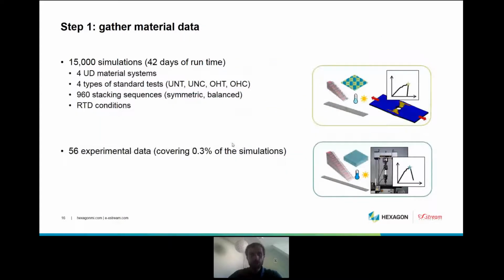Okay, so step one, like we mentioned, is to gather the material data. Here, what we have done in the following exercise is perform something like 15,000 simulations. So it's approximately 42 days of runtime. We looked at 4 different UD material systems, 4 types of coupon tests, so unnotched and open hole tension compression, 960 different stacking sequences, which were symmetric and balanced, and we kept to the room temperature dry conditions.